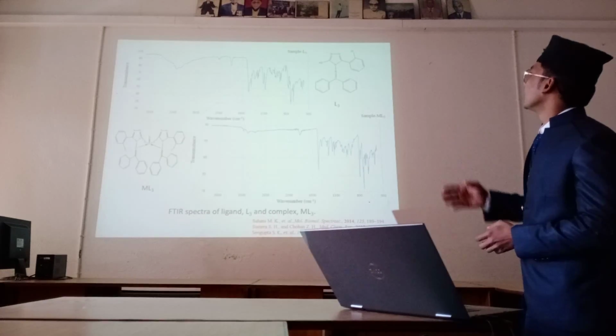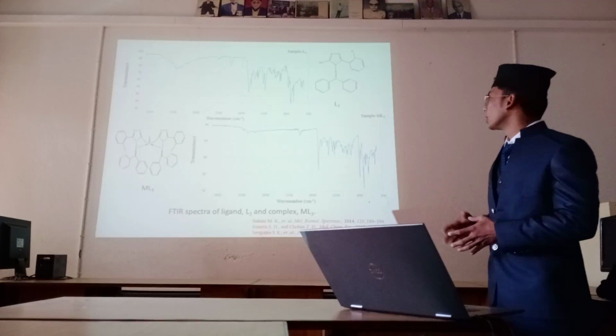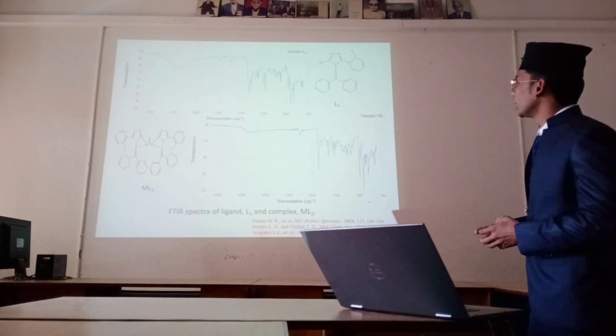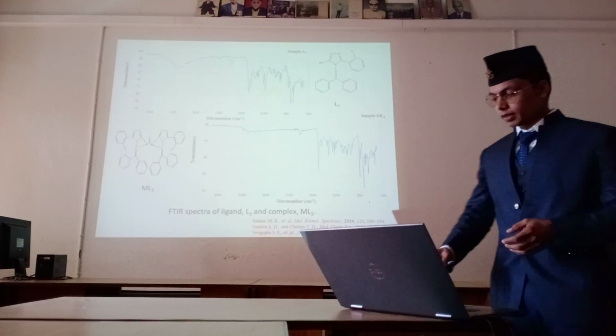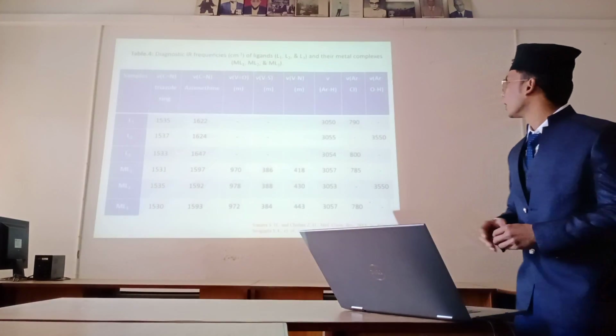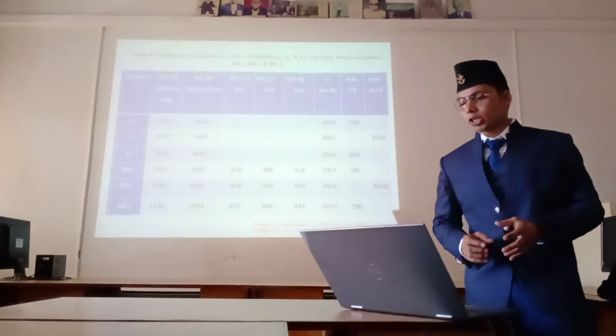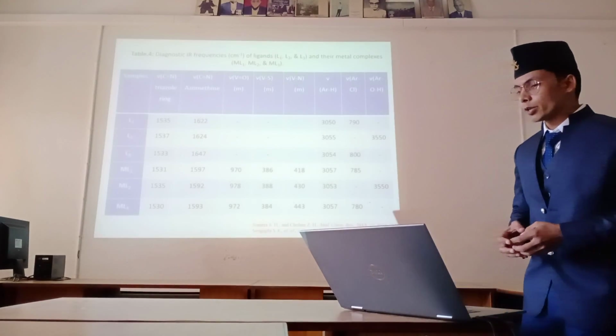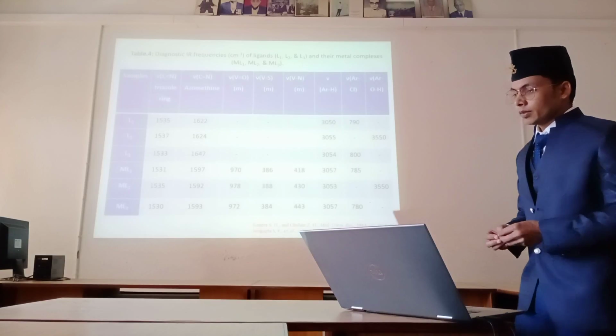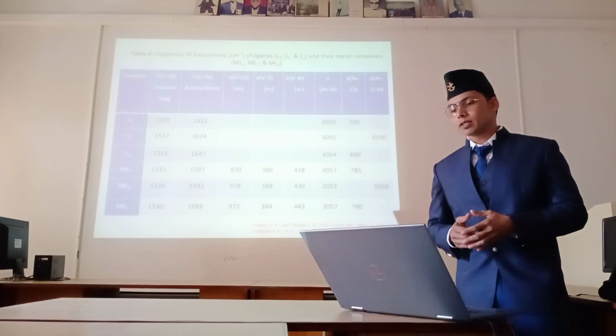Similarly, here we can see the expected structure of the third ligand and its FTIR spectra, and the third oxovanadium(IV) complex and its spectra. From the analysis of the IR spectroscopy, we can find that the spectral band near 1620 to 1650 is due to the C=N double bond stretching in all cases of the Schiff base ligands, due to the stretching of the azomethine group, and this value is found lower in the case of the complexes, indicating the nitrogen to metal coordination bond.